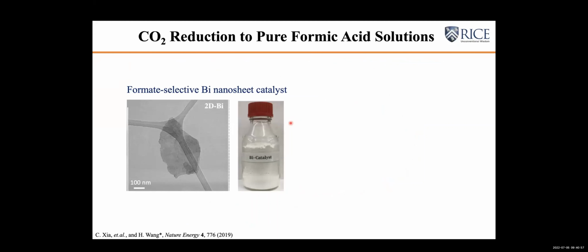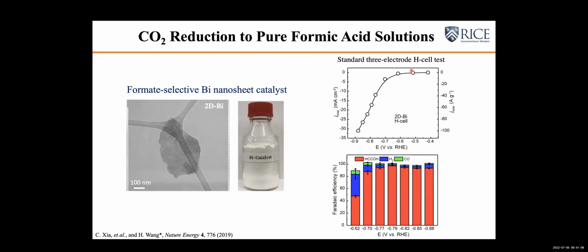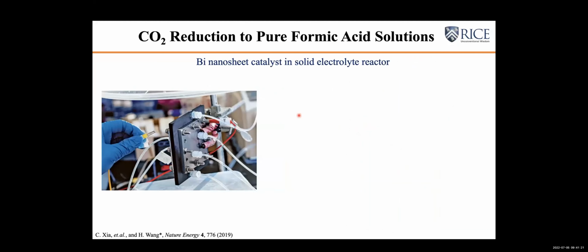To demonstrate this concept, at the very beginning, we synthesized this two-dimensional bismuth catalyst, which is very selective to formate. This can be seen from a traditional H-cell type test: within tens of milliamps, we can get over 90% formate selectivity. Only trace amounts of hydrogen and CO can be detected. This high selectivity can be successfully translated into the solid electrolyte device. This is the photo of the very first version of the solid electrolyte reactor, where the middle plate is the solid electrolyte layer, with cathode and anode on both sides.